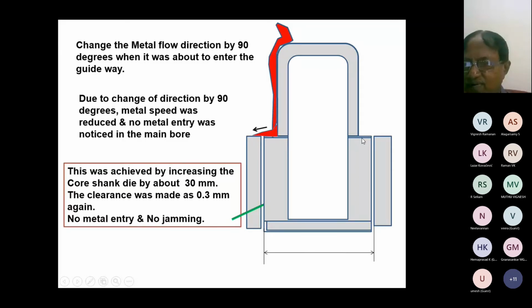All over the place, it goes like that. This is a very great idea. First time tried, but the diameter is very unconventional. Normally, instead of 2 mm, we made it 30 mm. There was no metal entry, there was no core jamming. But there was another problem. If the core shank is more, the casting goes down along with that.